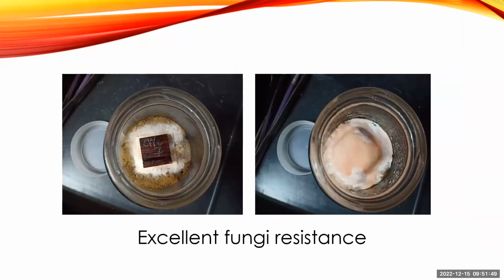Here are some results we would like to share. The resin treated plywood made from this process has excellent fungus resistance. After 8 weeks of exposure to white rot fungi, the surface of the resin treated plywood is completely free of white rot fungi.